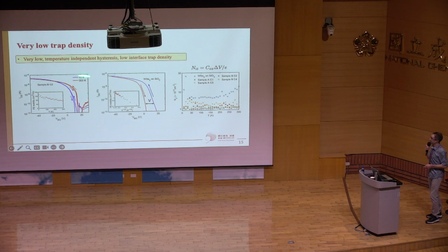Now, if you compare, so this is our sandwich structure compared to our control structure of WSe2 on silicon wafer, we see that the hysteresis here is quite big, and we can compare the data from those two plots here just by converting the difference between the forward and backward sweeps to a trap density using the capacitance formula. And here we see for our encapsulated devices, much lower and temperature independent trend.